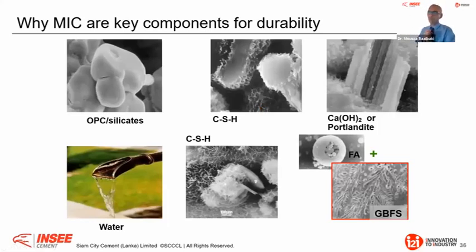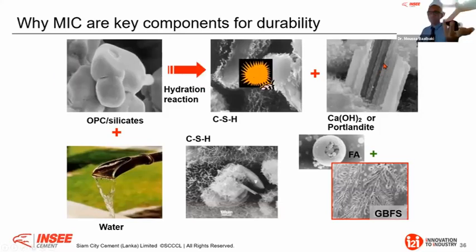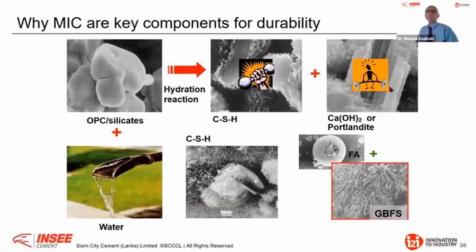I have presented this to some of you, but for those who have not seen it, when I talk about the hydration reaction from OPC, we can see the silicate phases. In the presence of water, you form the calcium silicate hydrate, the CSH: very small fibers in the microstructure, where the length is below 50 nanometers, as I said. And you have portlandite, which are big crystals. Now, strength comes from calcium silicate hydrates, and very often you have difficulty in terms of durability because these are soluble. Even though they are important to keep a certain basicity for concrete, a certain pH to protect reinforcement, too much of this product will also create other big problems in terms of durability.